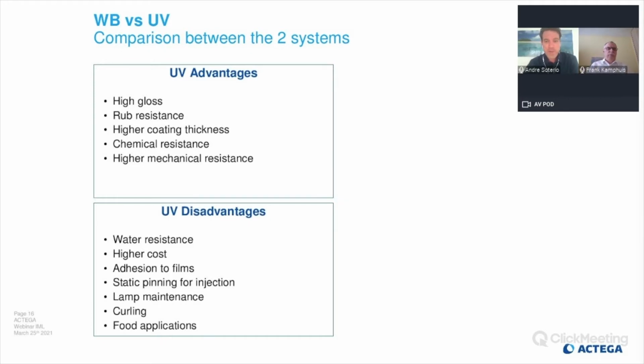But UV also has its disadvantages. Although we think that UV has a very good rub resistance, UV coatings have a very low water resistance. So this is one of the really big disadvantages when using UV coatings. The second one is the higher cost compared to water-based. The third one is adhesion to films. Depending on the film treatment and the application way, sometimes you can have some adhesion problems, and you will need to use a primer for improving this adhesion, which means an extra product.